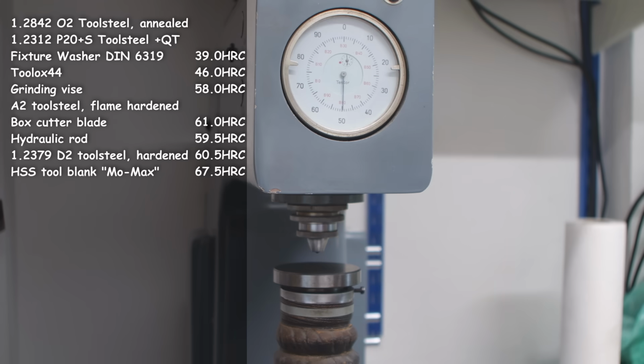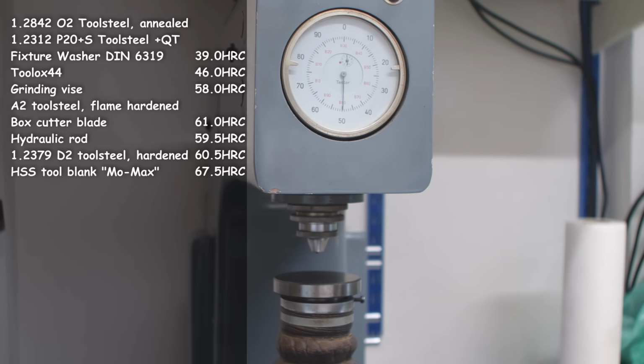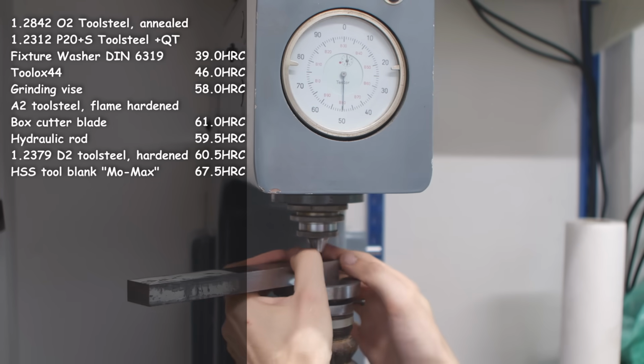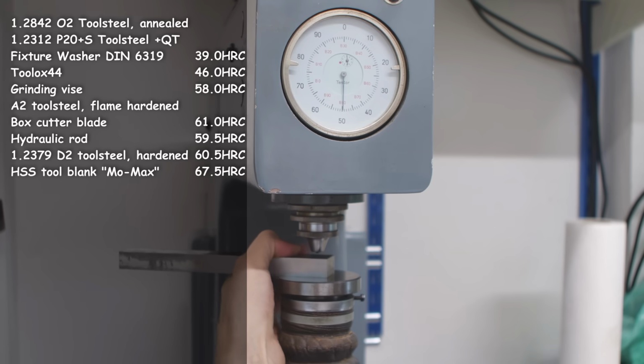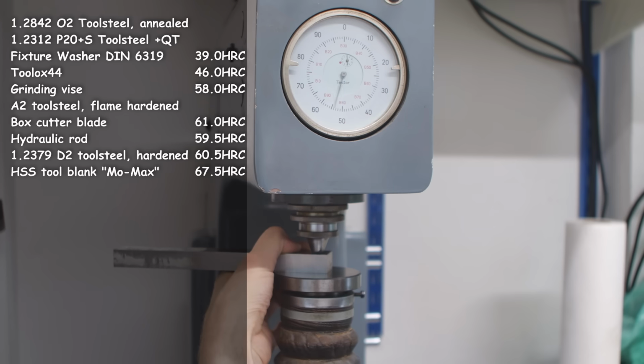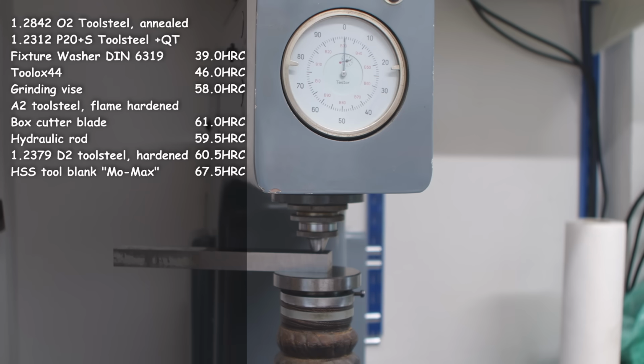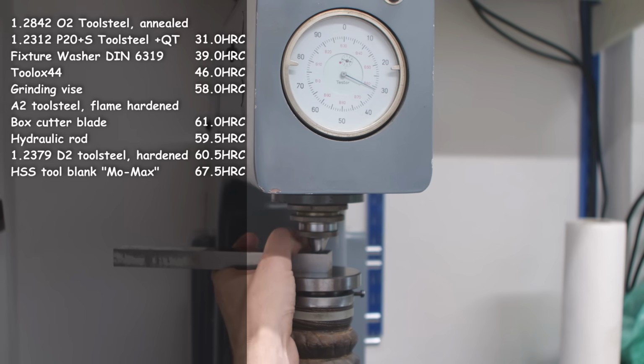Next one, P20 plus S 12312, which is a tool steel that usually comes in a pre-heat treated state. It can be used for all sorts of things. I made lathe tool holder blocks out of it in the past because it comes with a nice toughness and a little bit of hardness. It's a fairly good material and machines beautifully, but it's not really hard. With high-speed steel tools, it's super easy to work with. It comes out at 31 Rockwell C, so not amazing, but also nothing to sneeze at.